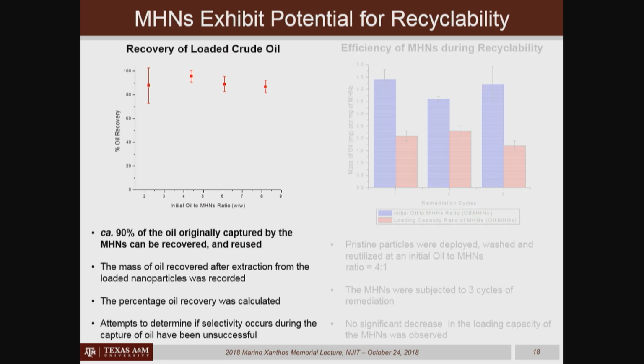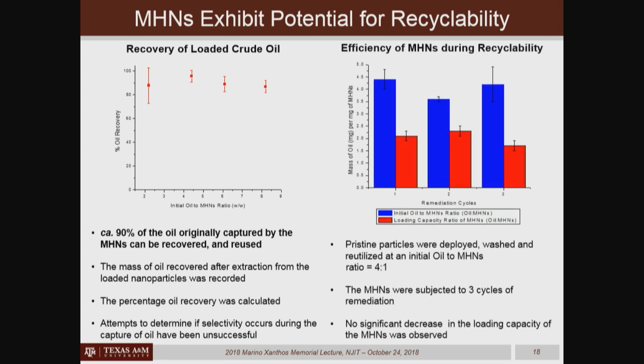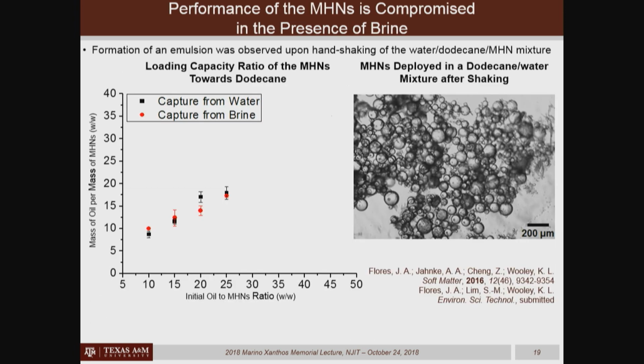And when she recycled them, then she found that in a first pass, they were able to capture a certain percentage of the crude oil, and they performed about the same in at least 3 iterations. So they are recyclable materials. So then Jenny was interested in increasing the amount of crude oil that could be captured by her materials. And she also was interested in addressing questions that we were receiving from people about, well, you've shown how they perform in water, but how about salt water? How well will they perform, say, in the Gulf of Mexico or in a saltwater environment?